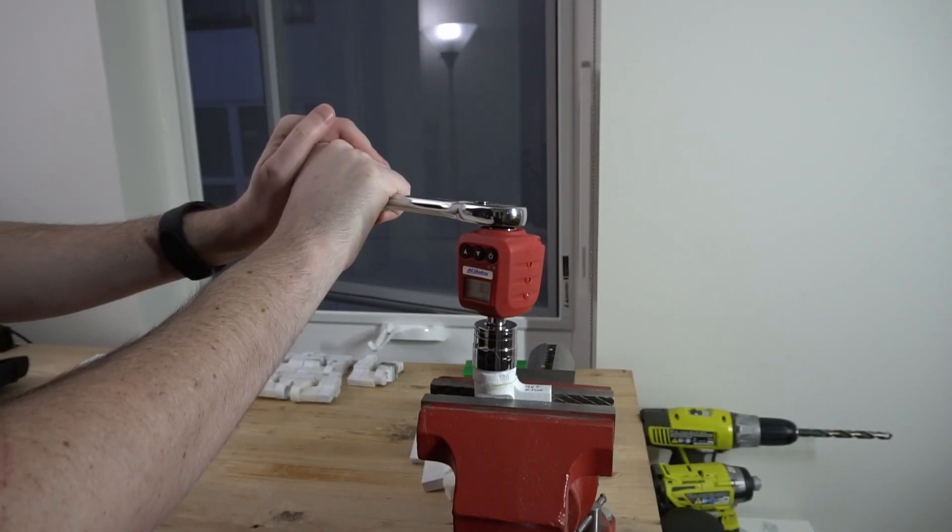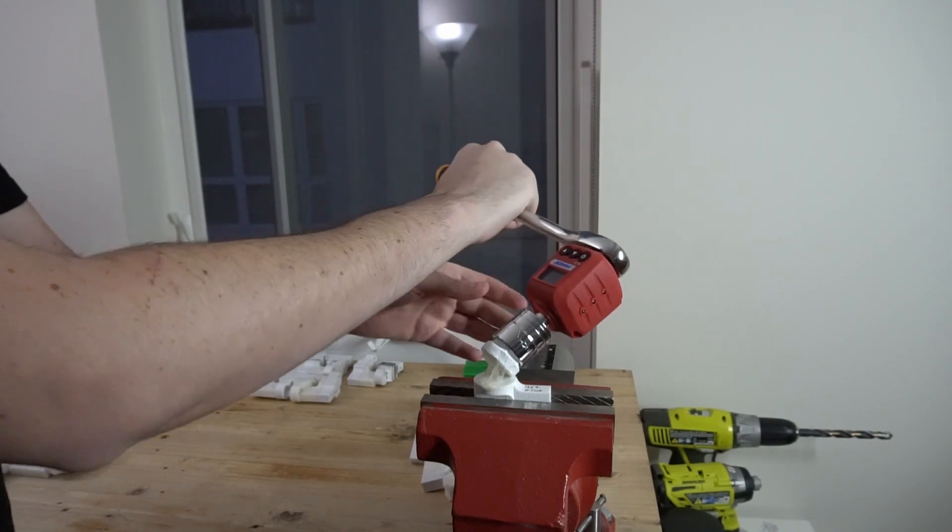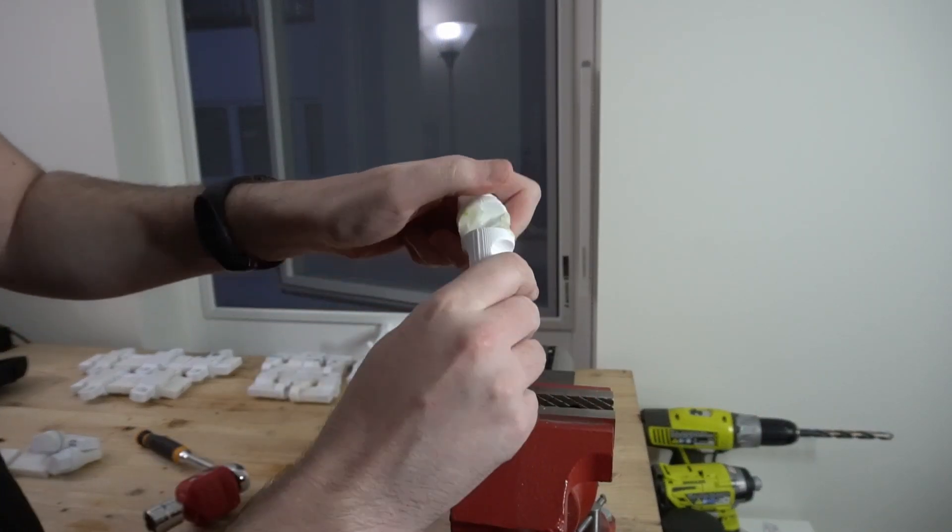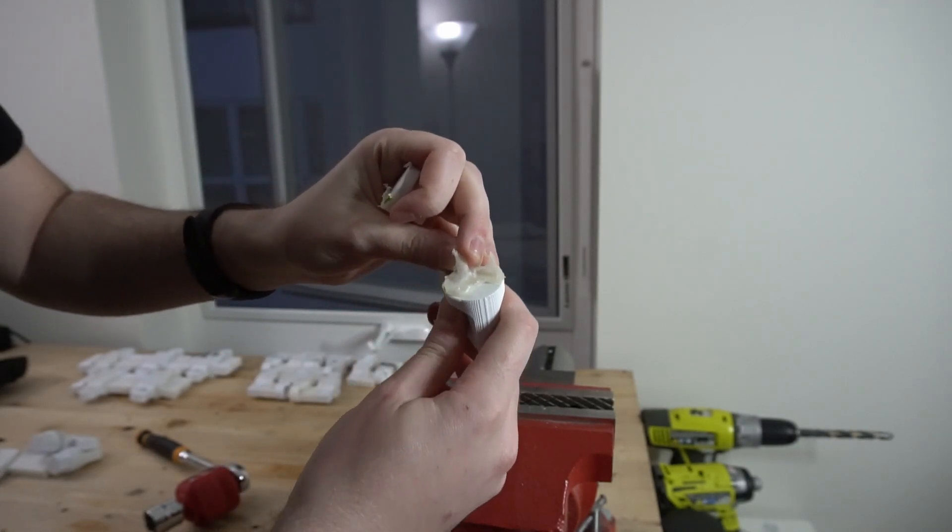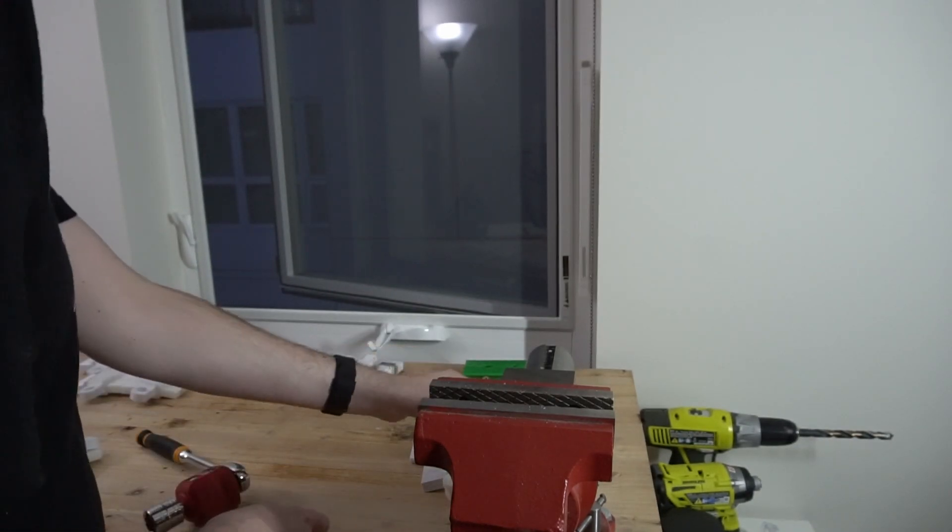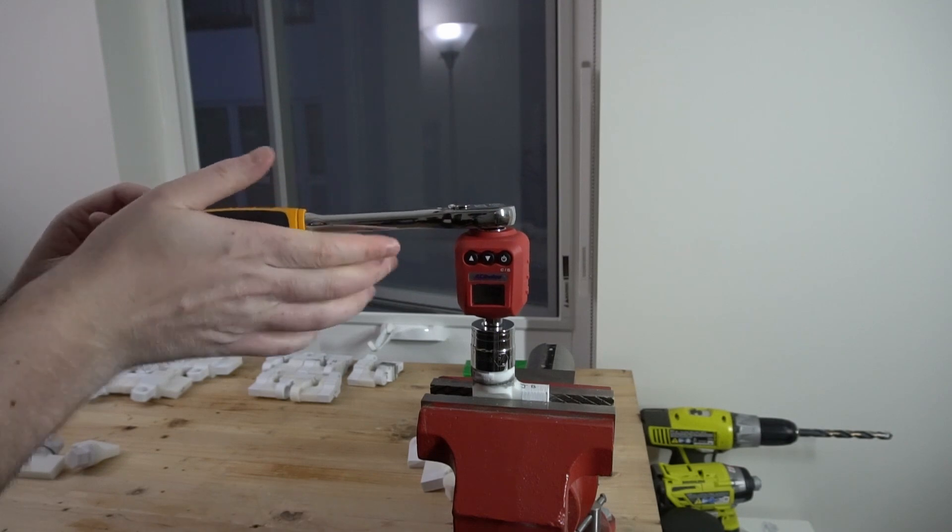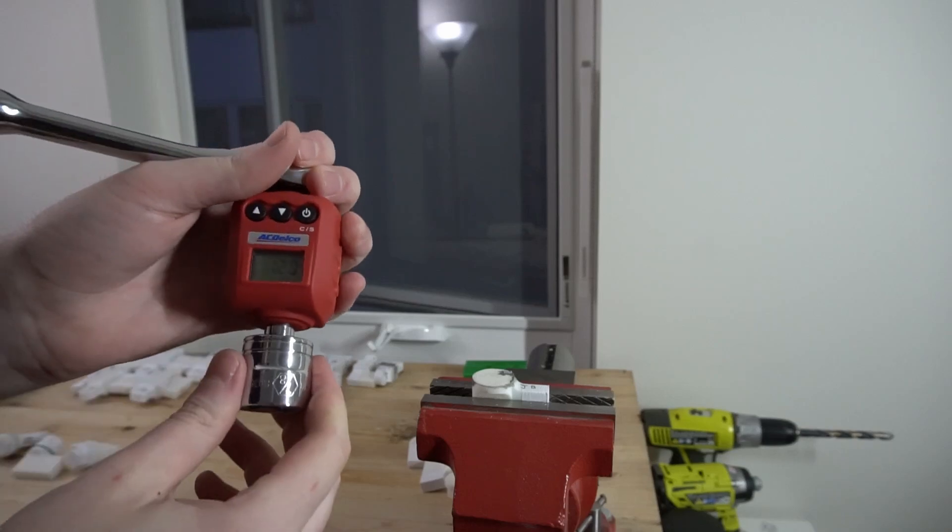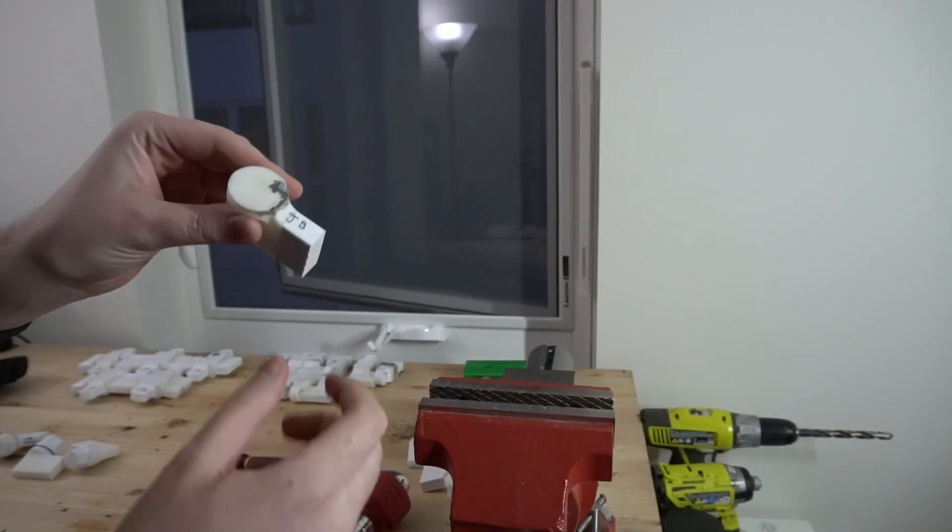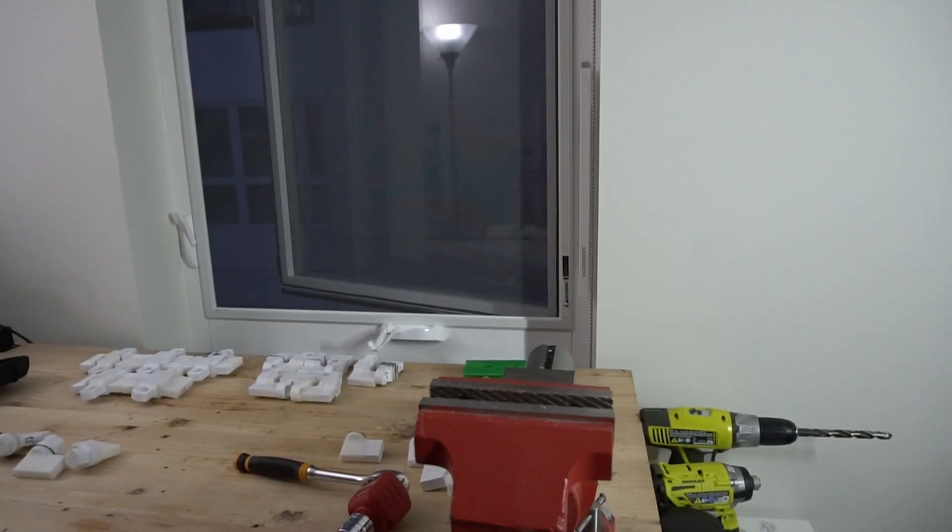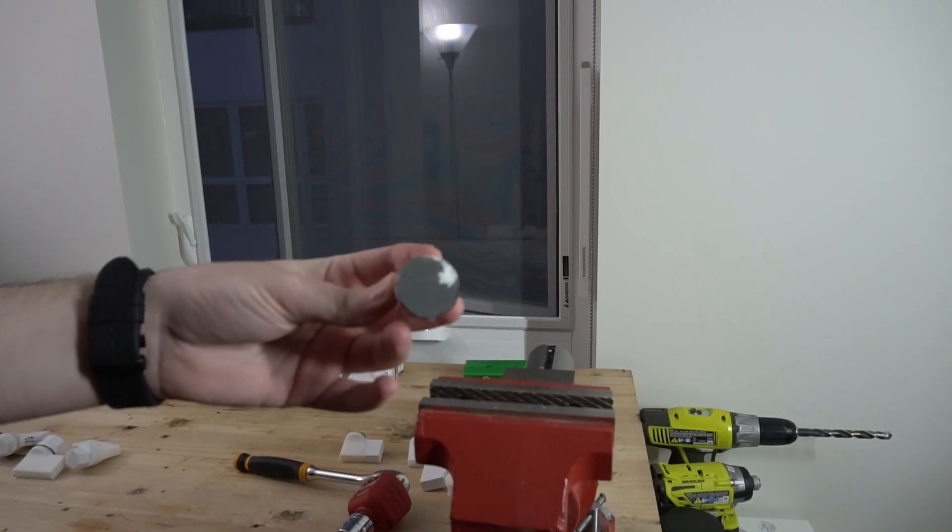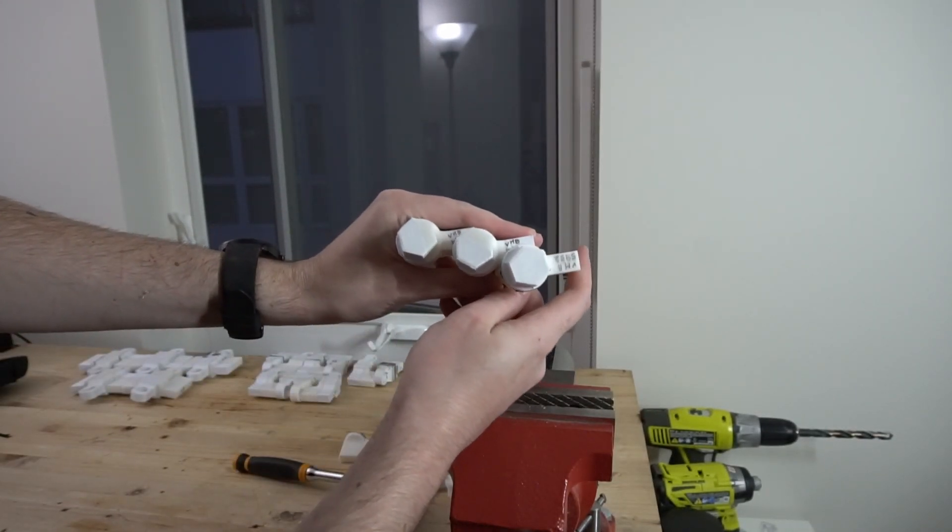Next up we have, I believe this is hot glue. And hot glue did a pretty amazing job, better than what I expected, at 11.2 foot-pounds. And you can see it clearly held on to both sides of the plastic, which is really good to see for an adhesive. I think that has to do with it melting the plastic just slightly. And then after, we have JB Weld. And JB Weld managed 12 foot-pounds on the dot. Pretty amazing that hot glue is only 0.8 foot-pounds less than JB Weld. And you can see that it did stay on both sides of the plastic. It did stay on both sides, but predominantly stayed on one, but it did actually break the JB Weld epoxy.